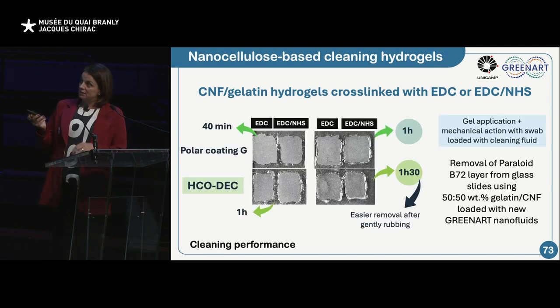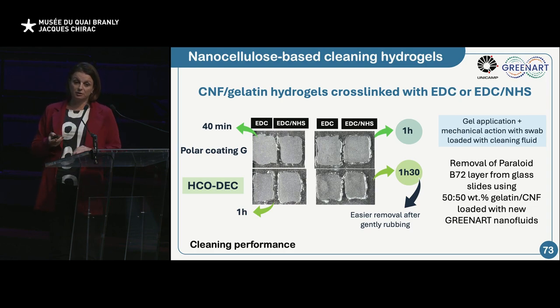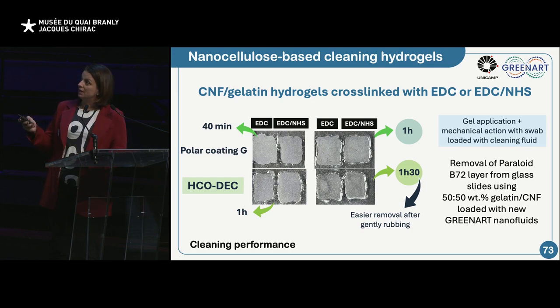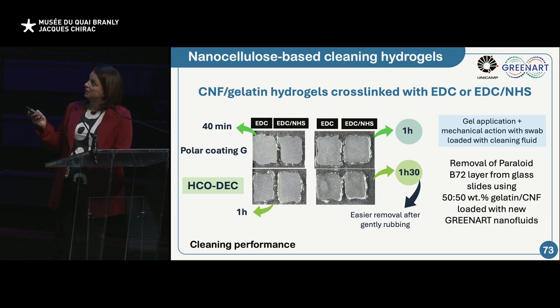We also tested these gels incorporated with Paraloid B72 and with the new nanofluids that were developed in the GREENART framework. Here are two examples of our gels tested for 40 minutes with Paraloid B72, and for 1 hour, and here 1 hour and 1 hour and 30.